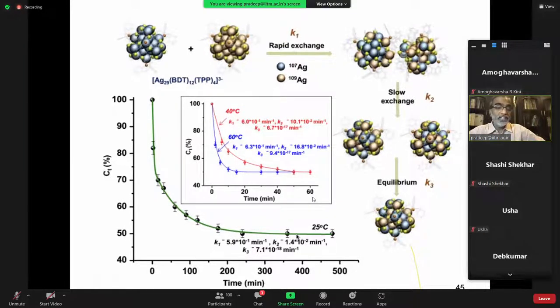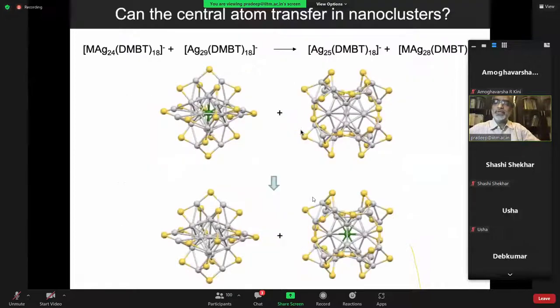And in fact, there are three different rate constants that you see. We interpret the first exchange as due to the surface atom exchange. And then there is the surface to interior transfer. And then there is an equilibration that happens. You have three different rate constants that you see. And overall, this kind of chemistry is comparable to the exchange chemistry that you see in other molecular systems.